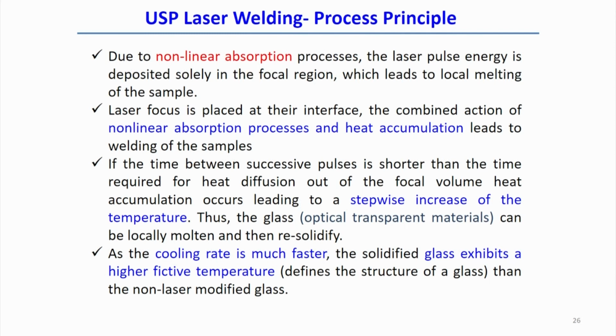So, therefore, the solidified glass exhibits a higher fictive temperature. That actually defines the structure of the glass. That is higher than the non-laser modified glass, because in the ultrashort pulse laser also there is a high rate of cooling we can observe.